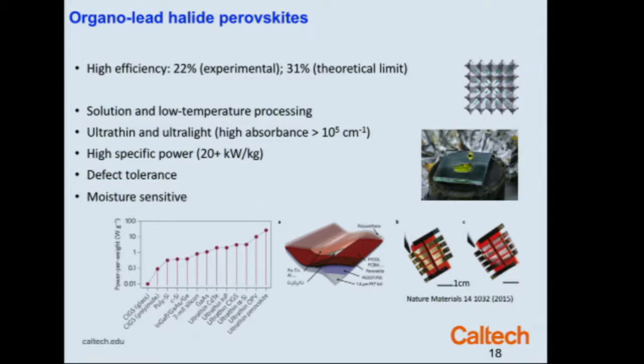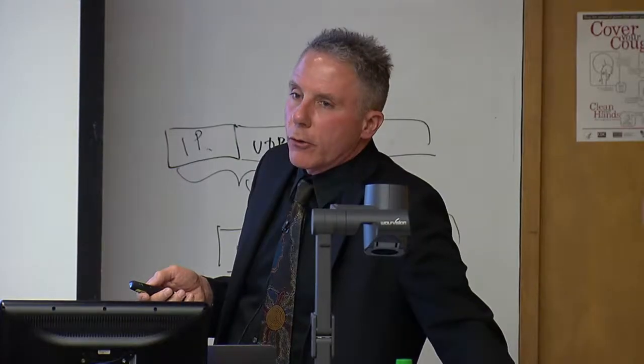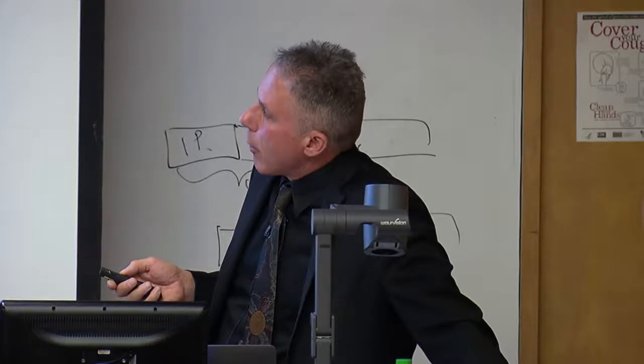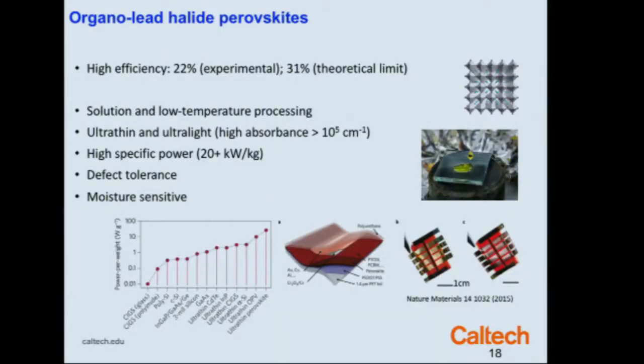They are seemingly immune to defects. In polycrystalline films, they have performance that rivals gallium arsenide in terms of the luminescence and the voltage performance. I showed that in some of the slides on Tuesday. They are very highly absorbing. You can spin coat them as thin films. You can doctor blade them. You can spray coat them onto polymers. And the thing that's remarkable is by putting them onto a polymer substrate, it's already been demonstrated that you could have a power density of 20 kilowatts per kilogram.